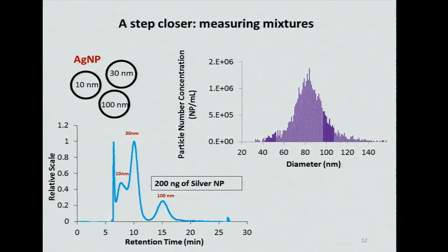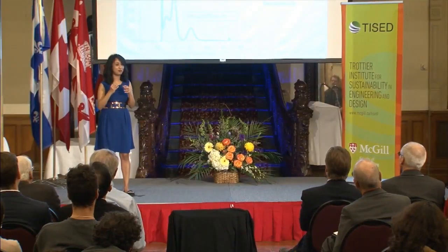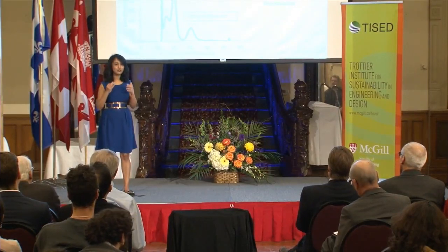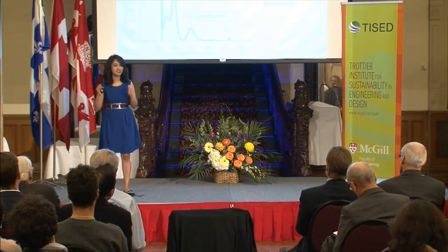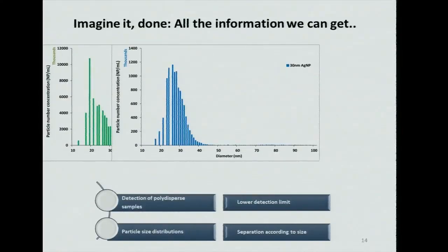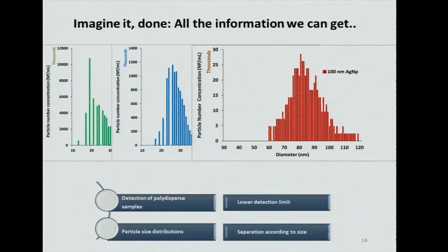Now going back to answering the river water question. It's great. So now if we were able to find a method where we first separate our particles according to size and then analyze them for composition and concentration, we would be able to get much more information. And that's exactly what we did. We collected the samples after analysis on field flow fractionation and ran them on SP-ICP-MS. So first, we got the 10 nanometer particles, followed by the 30, and then the 100.